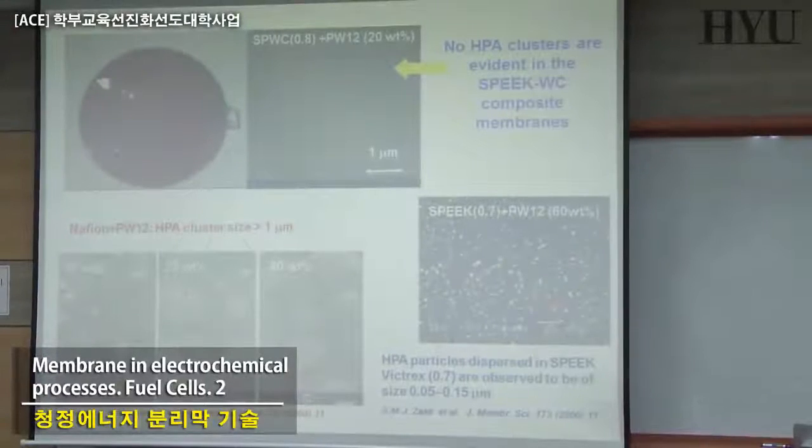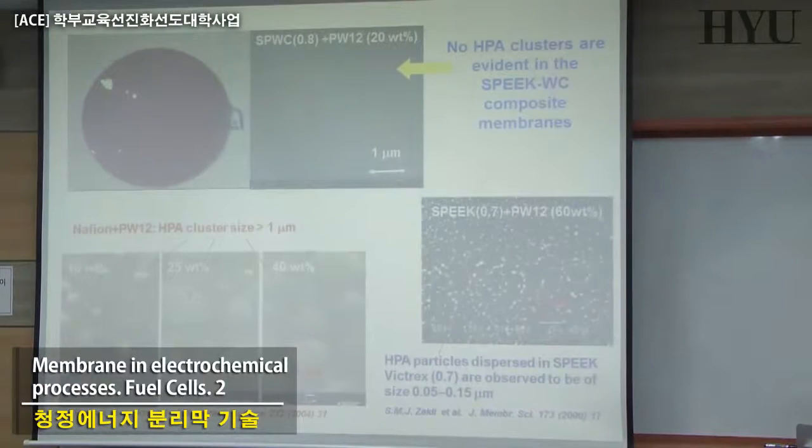In some other cases, the situation can be different. If you want to do the same with other materials, for example with Nafion, it is much more difficult, at least for us. You see here what we were already discussing, what we don't like to have: a big agglomerate with very heterogeneous distribution, etc. That is killing the performance, basically. With PEEK, the dispersion we can obtain is much better than the one you can have, for example, with Nafion. So from this point of view, it is a positive aspect. That's why we have been spending time and publishing.